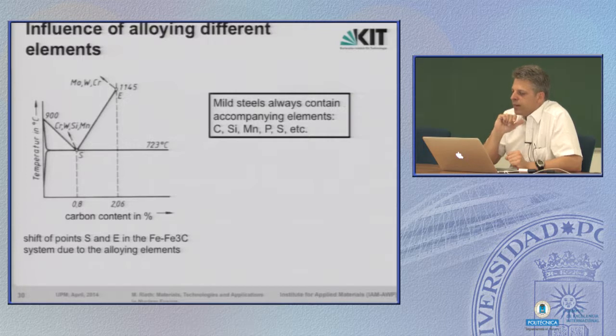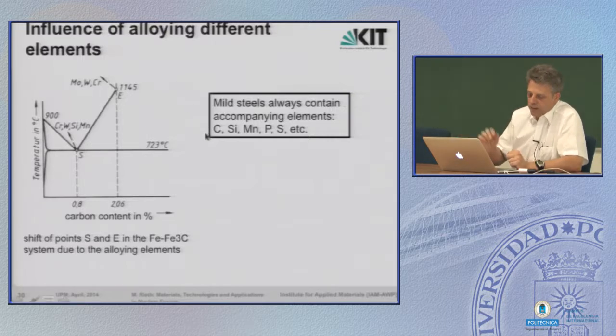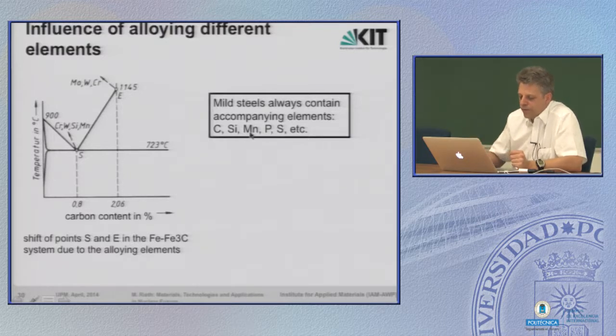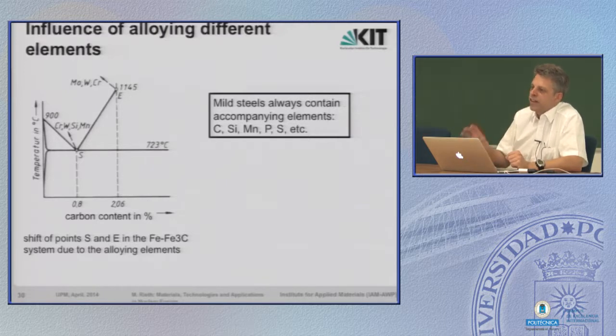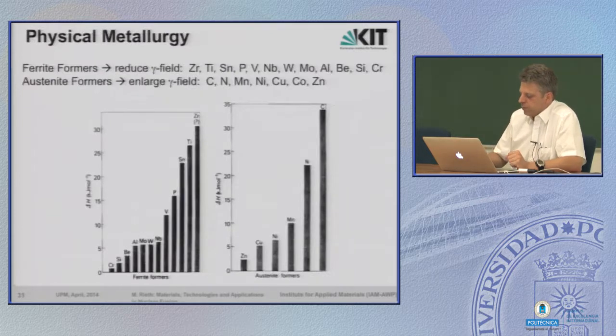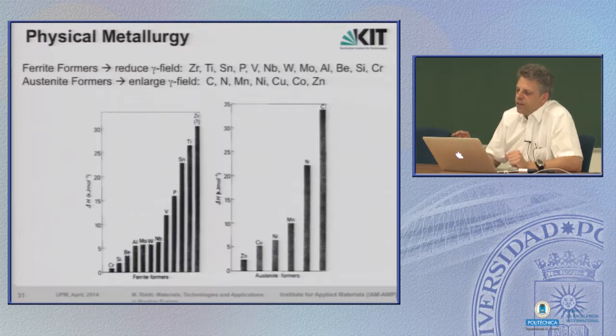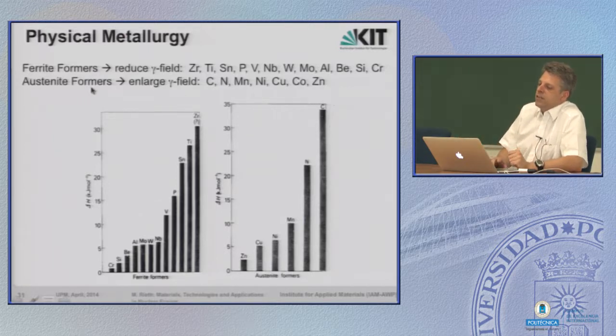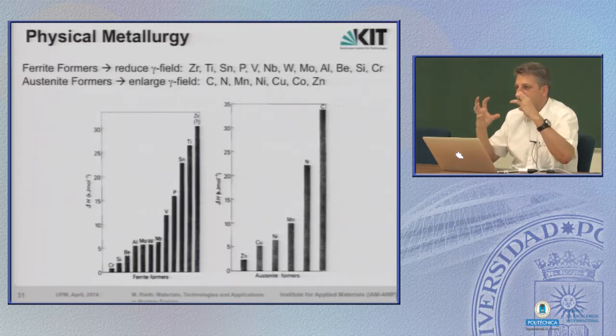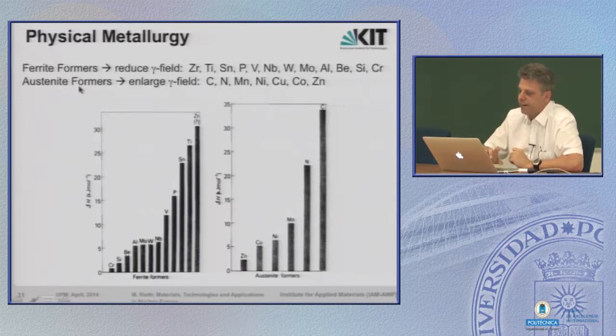We also have to keep always in mind that steels, or at least the mild steels, are not very pure. They always have a certain amount of carbon, silicon, manganese, phosphorus, sulfur, etc. inside. That's the so-called accompanying elements. To get rid of them needs a special treatment during production. In general, the effect of different types of elements as alloying elements in steel are subdivided into two categories. One are ferrite formers, the other ones are austenite formers. Ferrite formers, they reduce the austenitic field, the gamma field. If you add elements of this kind into the steel, then the gamma phase field is reduced significantly.